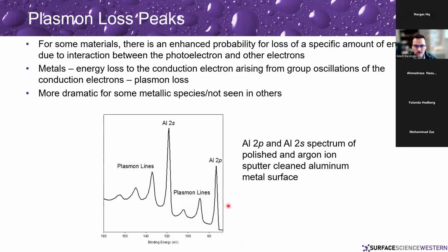Generally, it's not too much of a problem for curve fitting of high resolution spectra, but in your survey spectra, a lot of times what we'll see is people will think, okay, this is another species. And we say, well, is this peak silicon? Is this phosphorus, etc.? When it's not, it's actually just these plasmon loss structures that are showing up.